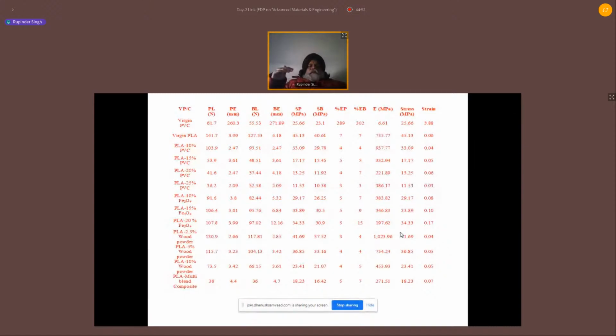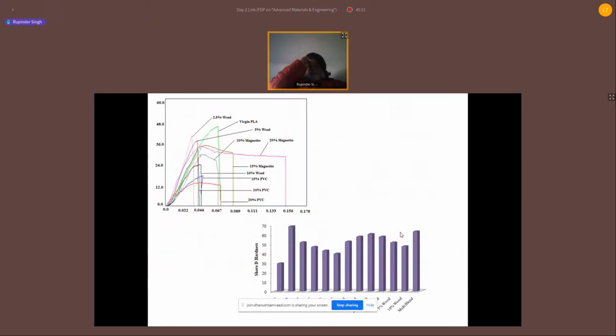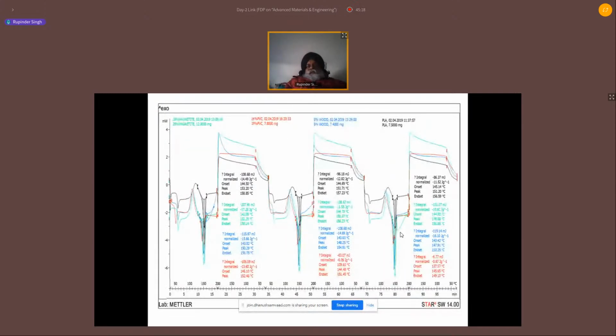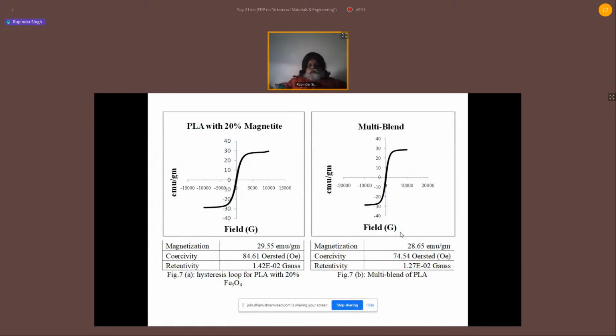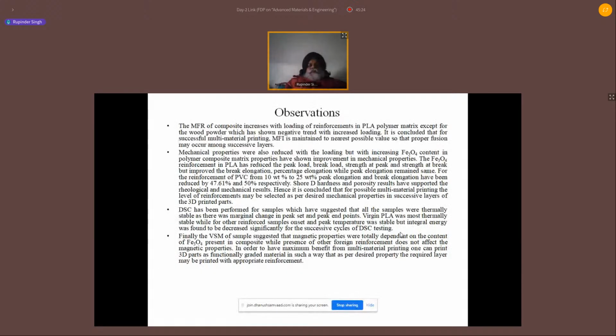We also try to observe, with these types of reinforcement, what the peak load, peak elongation, break load, break elongation, peak strength, break strength, percentage elongation at peak, percentage elongation at break, then Young's modulus, and of course the modulus of toughness also. We look at the area under the curve, then their surface hardness in the form of Shore hardness, again their thermal stability, and different BH curves for different types of materials. So what we observed is we were really able to develop multi blend materials with respective magnetic, thermal, and mechanical properties.